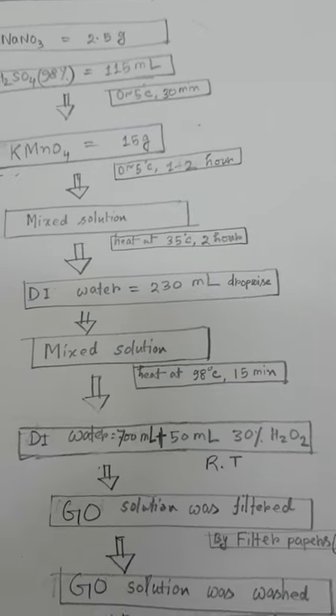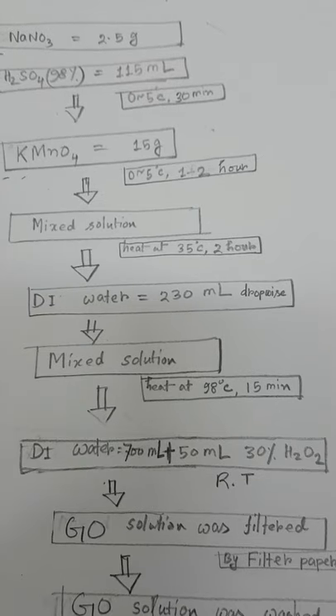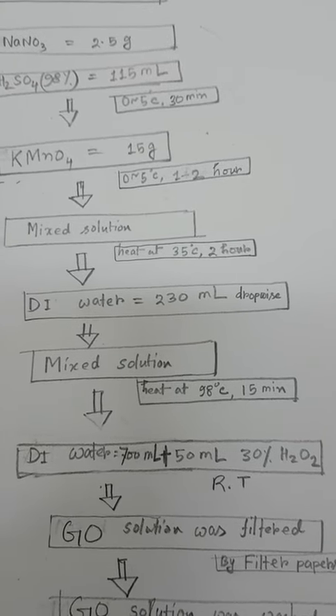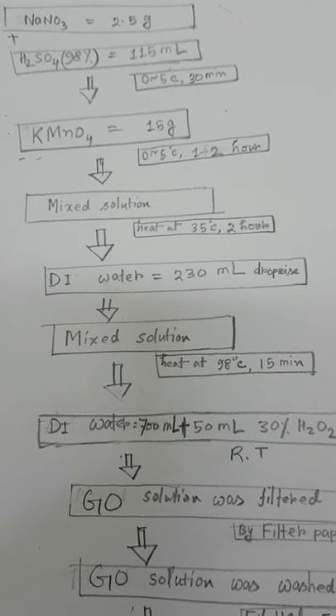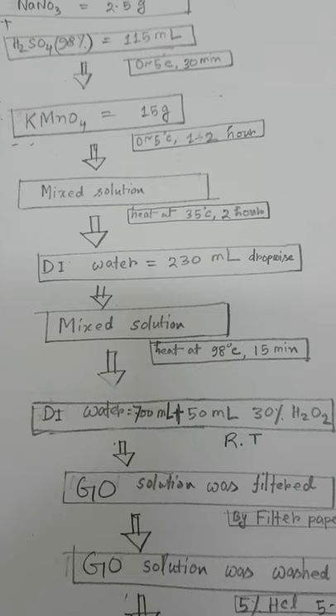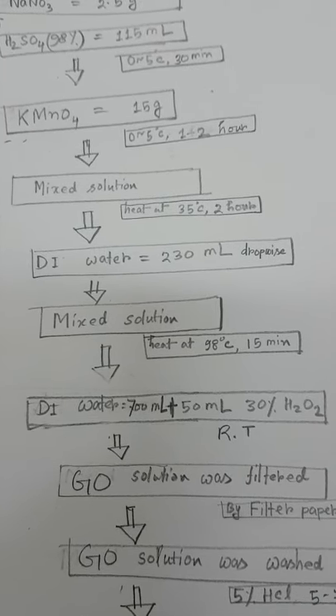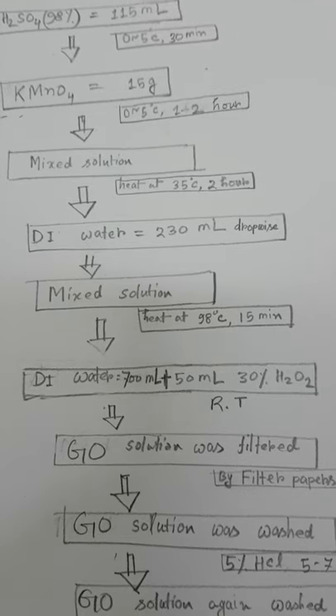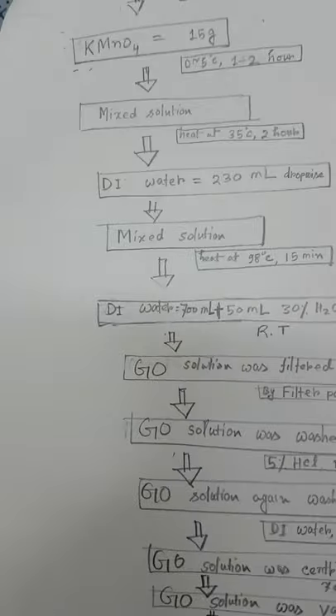Then I added DI water, 230 ml drop-wise, and then transferred it to high temperature at 98 degrees Celsius. The mixed solution was heated for 15 minutes, then I terminated the reaction.